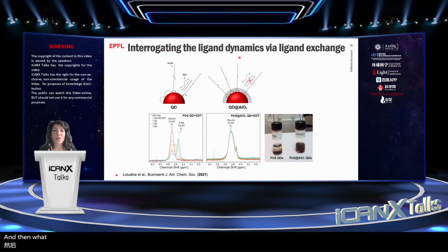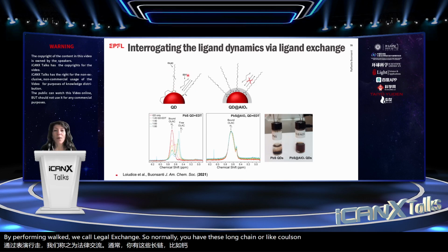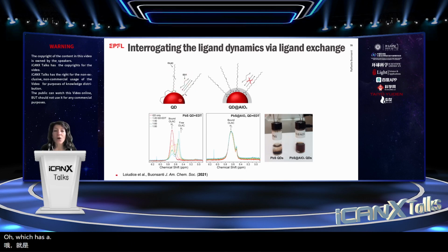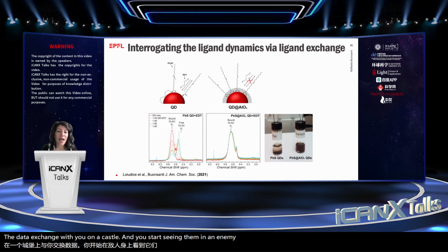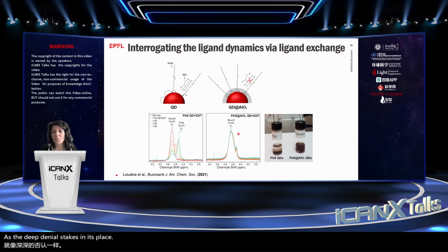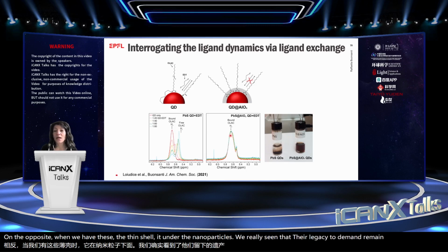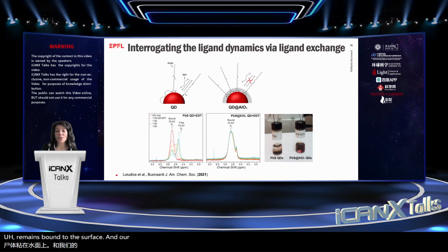And then what we tested is the ligand dynamics by performing what we call ligand exchange. So normally you have this long chain oleic acid. When you add a dithiol, which has a stronger affinity for the quantum dot surface, the dithiol exchanges with the oleic acid, and you start seeing in NMR the free oleic acid appearing as the dithiol takes its place. On the opposite, when we have this thin shell around the nanoparticles, we really see that the oleic acid remains bound to the surface. And our solutions are indeed much more stable compared to the uncoated sample.